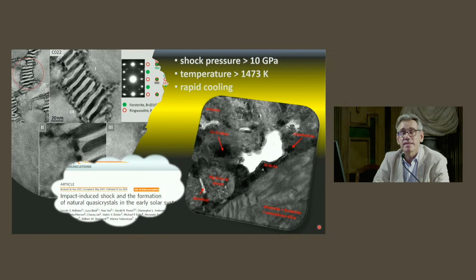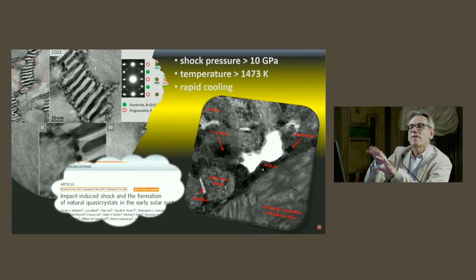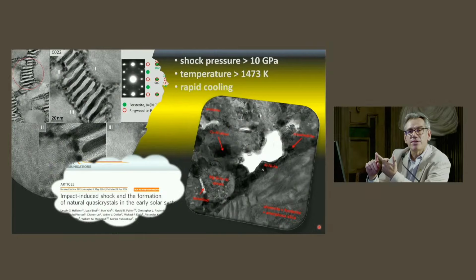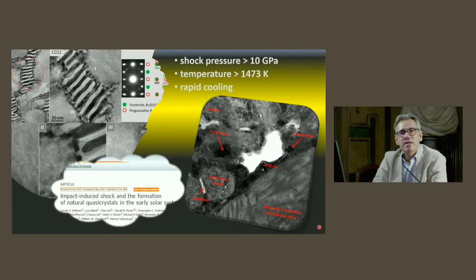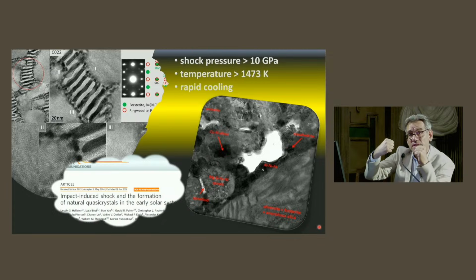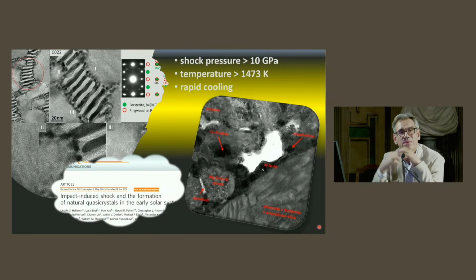Olivine is a magnesium silicate, one of the most common minerals in our mantle. So the presence of stishovite and ringwoodite, two high-pressure phases, along with all the other petrographic features you can observe here, are all indicative of very high shock pressure, very high temperature, and even more important, super fast cooling. With this kind of image, we proposed, more than 10 years ago, the first hypothesis of formation of quasicrystals in space, through collisions among asteroids in outer space, which produce the conditions able to form these kinds of materials.